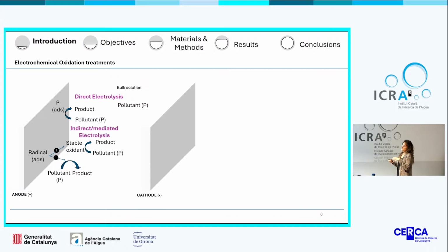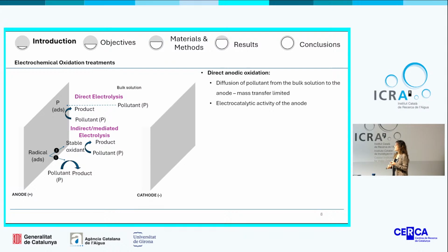For that reason, we decided to focus our attention on electrochemical oxidation treatment. Electrochemical oxidation treatments are based on the induction of current into the working electrode, which is the anode, to oxidize different contaminants or pathogens, while simultaneously the reduction reaction occurs in the cathode. This oxidation process can be performed in two different ways. Direct anodic oxidation, in which the contaminant is adsorbed onto the surface and directly eliminated. This process is mainly limited by the diffusion of pollutants from the bulk solution to the anode and the electrocatalytic activity of the anode.